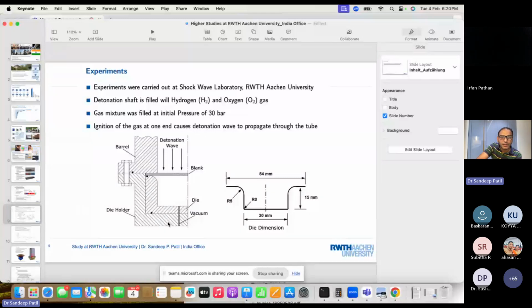Therefore we also have a die holder, which has a vacuum vent at the bottom, so you can make sure that no negative pressure is created at the end, which would cause an issue for the blank and keep it from forming correctly in the shape. So we made this vent. And as I said, the inner dimension of the die was 54 diameter, outer diameter 30 millimeter inner diameter, and then other dimensions. So I'll just show you the next steps.